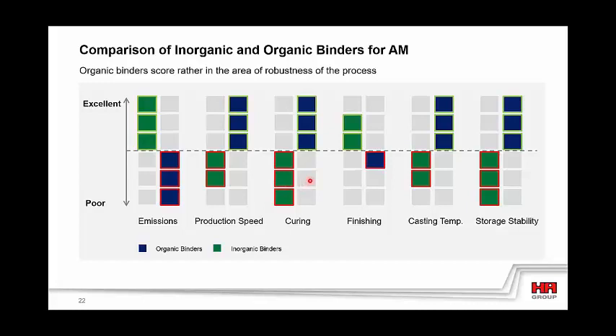Comparing finishing, during the self-curing of the furan binder, a gas push occurs at the interface zone of the curing, and it leads to further unintended reaction of neighboring activated molding material. This manifests itself in unfavorable mold fidelity, which can only be corrected with appropriate care by the finishing. In the case of inorganics, the molding material is not pre-coated with a liquid and is therefore dry. This dry molding material in combination with the reduced interface zone reaction leads to a clear boundary and therefore to a better finish.